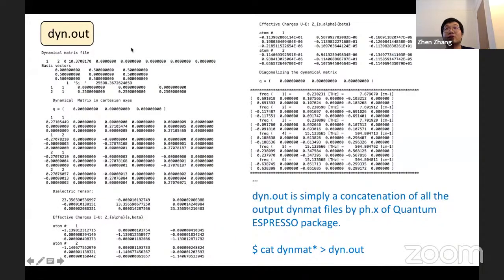Next is dyn.out. It's simply a concatenation of all the dynmat files by the ph.x executable in the Quantum ESPRESSO package. After we do the harmonic phonon calculations by using ph.x, the information of dynamical matrix at each Q point in the Brillouin zone is written to a dynmat file. Therefore, to obtain the dyn.out file, we can simply cat all the dynmat files together to get dyn.out.